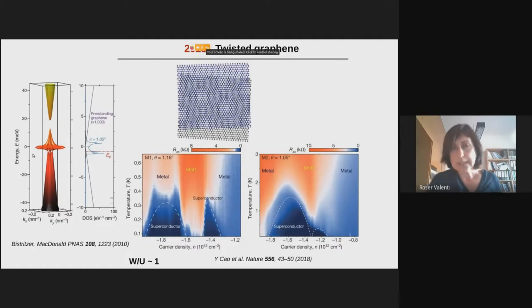So what happens then when you twist these two layers is that the band structure changes. And the band structure, what I'm showing to you, is the energy states that you expect in the reciprocal space of k, where k, if you think in a Bloch wave description, is basically the reciprocal space description. So these very flat bands of dispersion are going to allow the dispersion, so basically the itinerancy of your electrons, and the Coulomb repulsion to be of the same order of magnitude. And this is important because it's telling us that we are going to expect that the properties of the system are going to be similar to what we know from the correlated materials that I showed you previously.